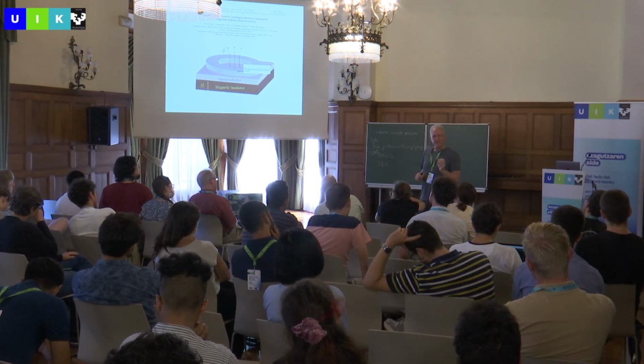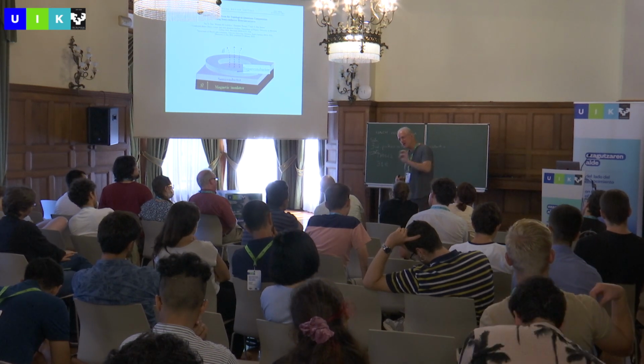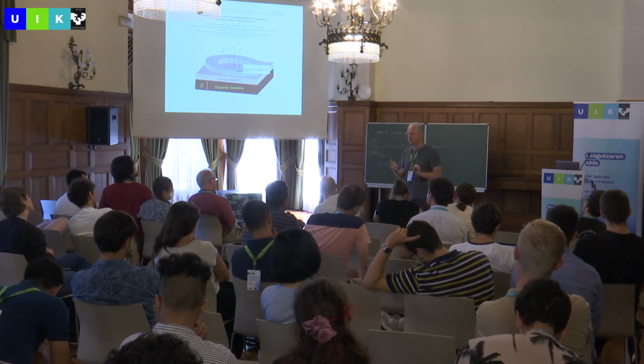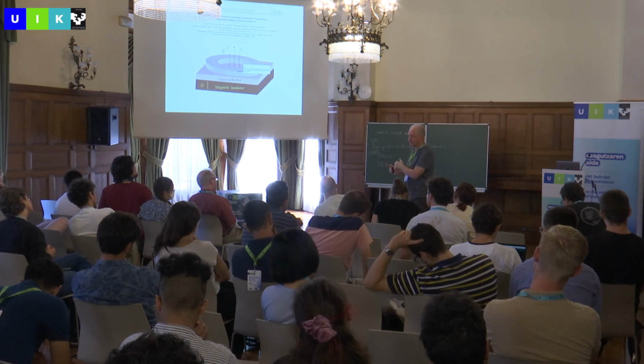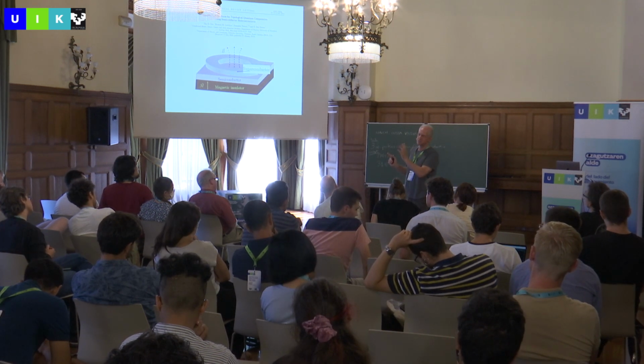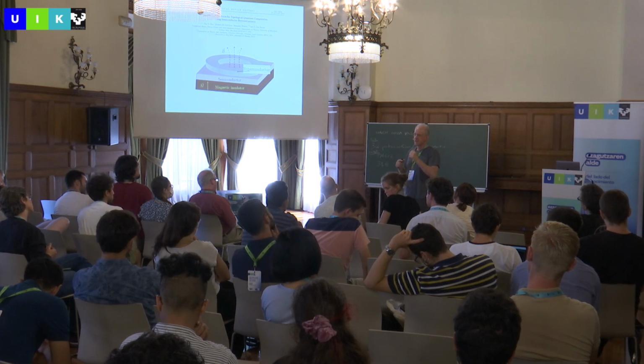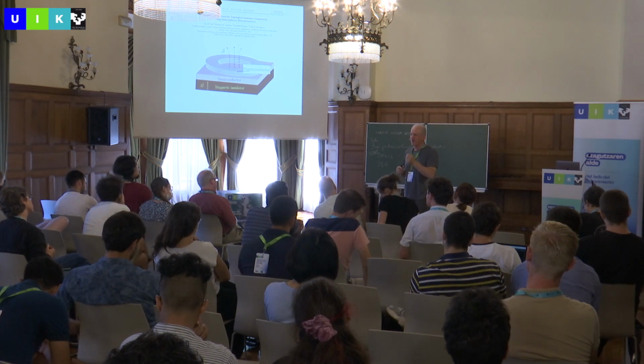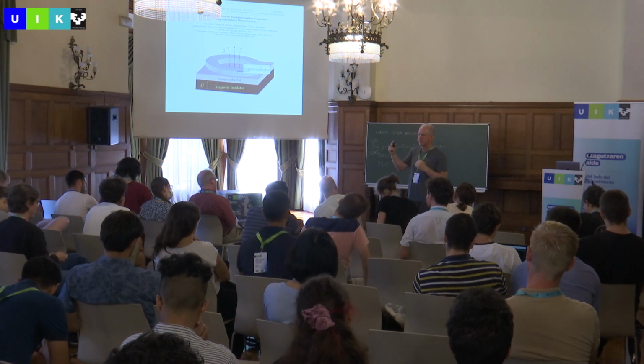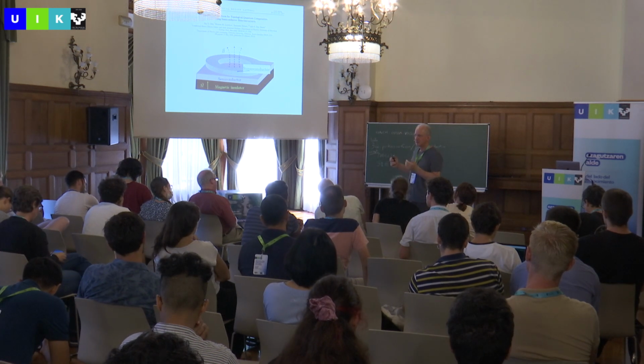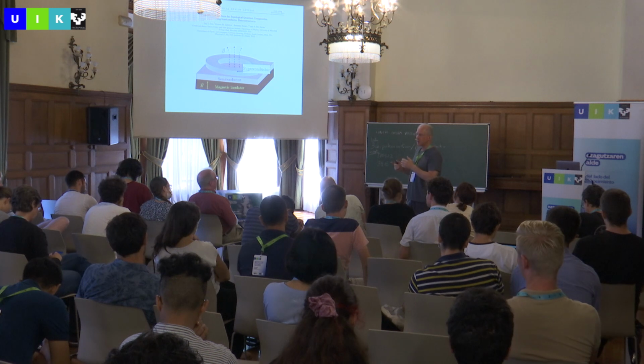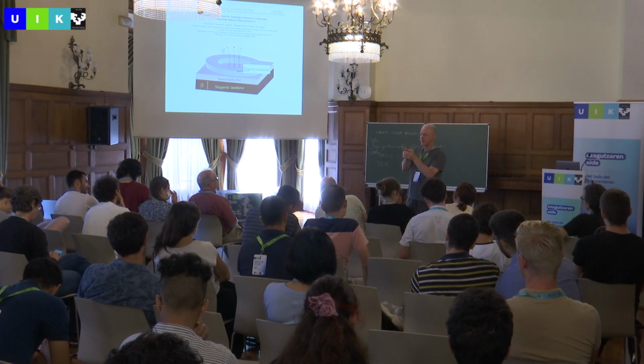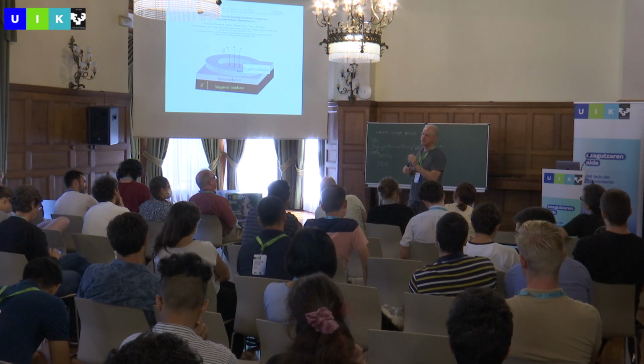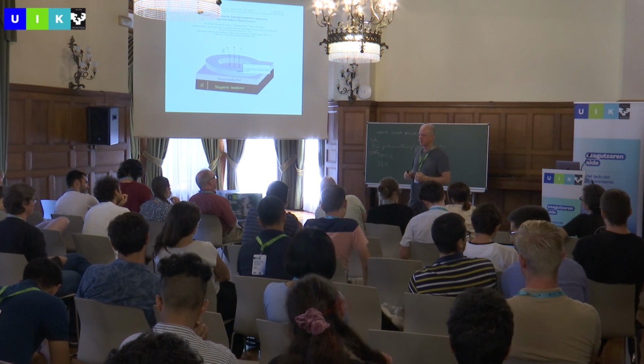So I need to have a system in which the material that is being proximitized, this wasn't emphasized in those early theoretical papers, but it turns out to be absolutely vital. Actually, it was, but it wasn't front and center. Absolutely vital that the G factor has to exceed by a considerable amount the G factor of 2 of the metal. So go find me an organic material, it's fine. And actually, I'm willing to give you back the spin-orbit coupling.